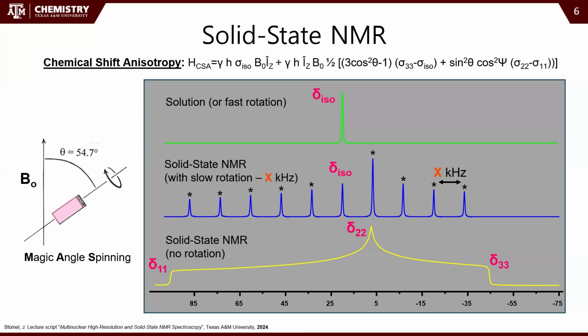So to reduce measurement time and increase our resolution, we use magic angle spinning. And so that's just turning the sample around at the angle of 54.7 degrees relative to the magnetic field. And that angle theta is here in the Hamiltonian of the chemical shift anisotropy. And so when we plug in 54.7, that 3 cosine square theta minus 1 term goes to 0. So that whole part of the chemical shift anisotropy is reduced.